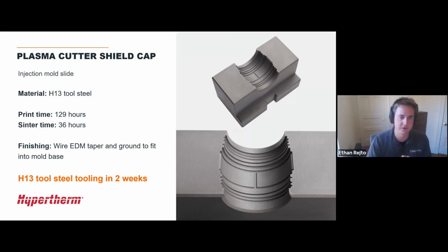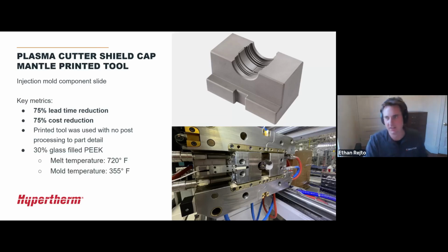They did have to do a little bit of finishing here. They wire EDM'd to taper, and they just ground the outside of it to fit into the mold base. All in all, it took them just 2 weeks to go from the tool design to actually running this in the press. You can see the part installed in the press here around the core component where it's forming the outside of that tool, and they were able to do this with a 75% lead time reduction and 75% cost reduction. The reason for that was because they used all of the printed detail with no post processing to that part detail. So where the mold is actually touching plastic, all of that was left as printed.